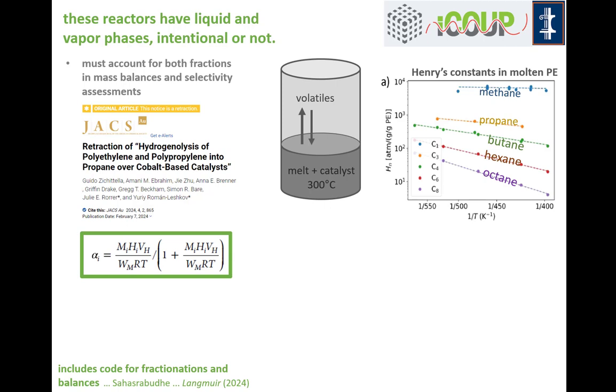There's a retracted paper with an unfortunate story — the authors did the right thing in recognizing that their assessment of selectivity to propane hinged on an assumption that the fraction of propane in the vapor phase would be the same as the fraction dissolved in the melt. That is not going to be true — Henry's constants for these species are all markedly different on a log scale. So it's important to keep track of those.